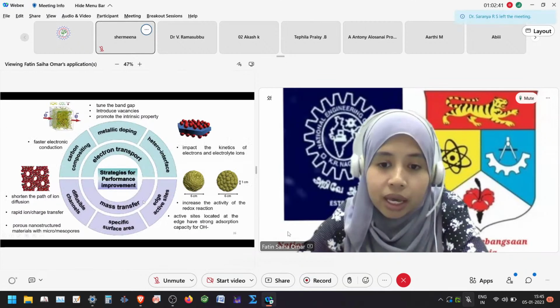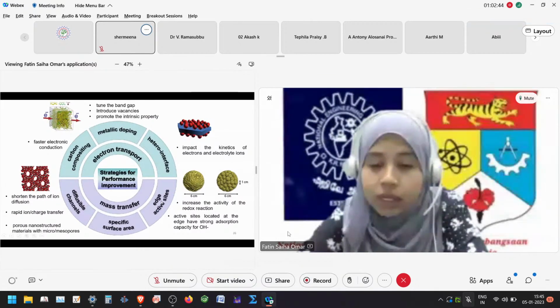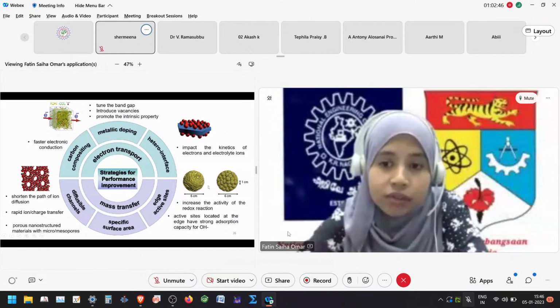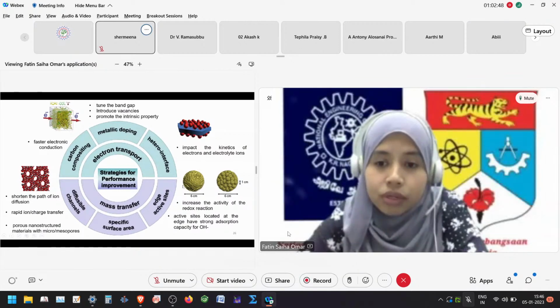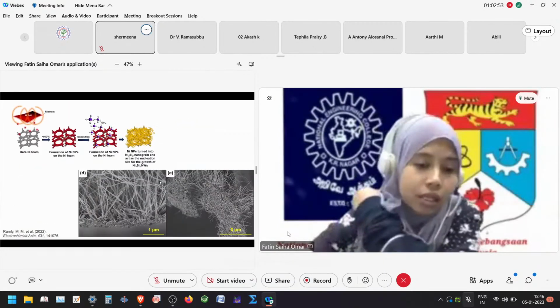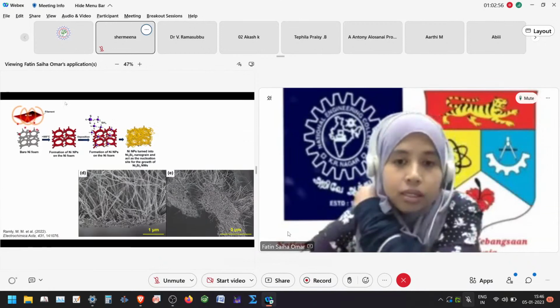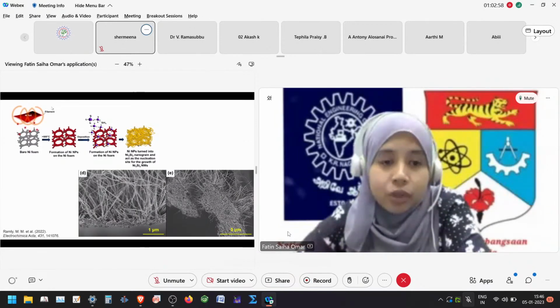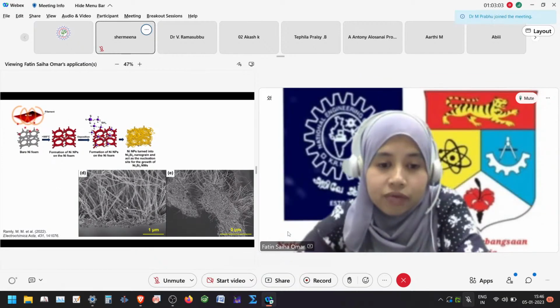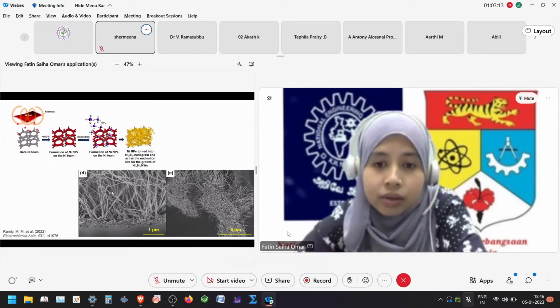And then we can also introduce edge active sites. For example, we can reduce the size of the particles from bulk to nano size. And this is the example. This is our recent paper where we synthesize nickel silicide binder-free electrode through the CVD method. In this first SEM image, it shows two layers. The first layer is the substrate, and the second layer is the nickel silicide nanowire.